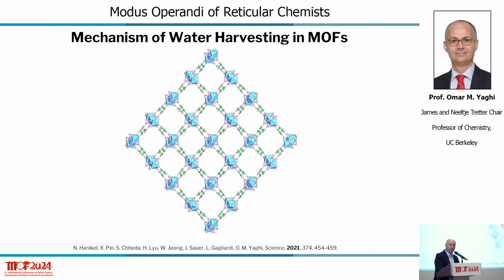That one, and then that one. And then they start bridging over the hydrophobic sites to fill the pores. Each one of these water molecules has been identified by single crystal X-ray diffraction. So this is not just a computational model, but is supported by experiment.